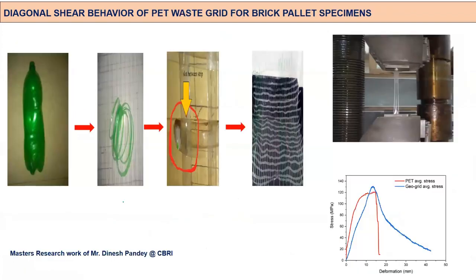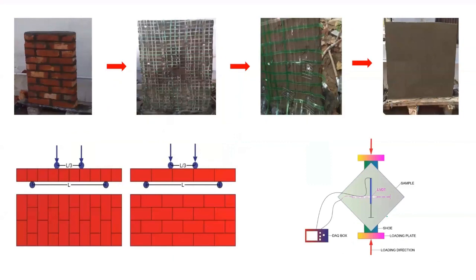Okay. So now, another study, we made a textile using a plastic waste bottle. You can see here, the plastic bottle has been converted into strip form. We converted it into a mesh form like this. And the individual strip testing shows that the modulus of PET bottle is higher than the modulus of grid material. But the post-peak degradation is sudden. Why we have done this study is, why can't we reuse this kind of PET water bottle waste, because it is available everywhere. And the mechanism of making the grid is very simple. Anybody can use this. And that's what the study was.